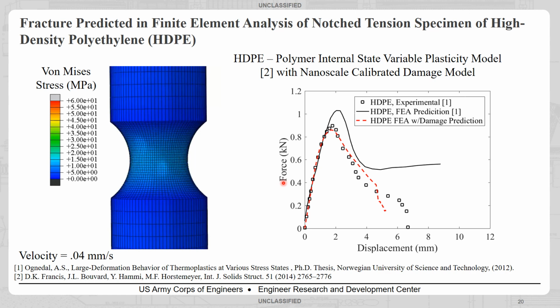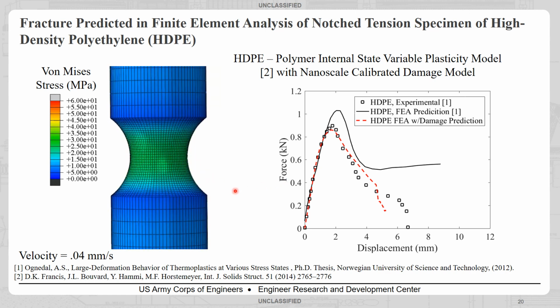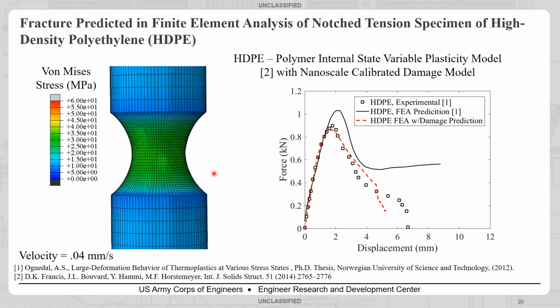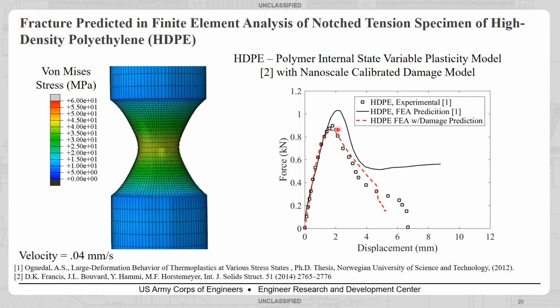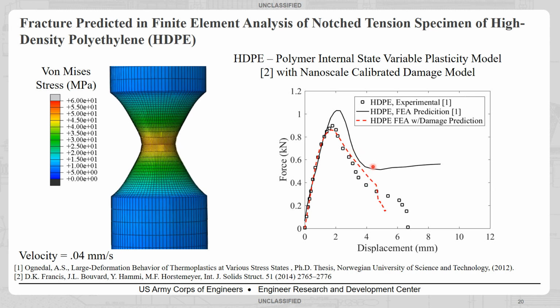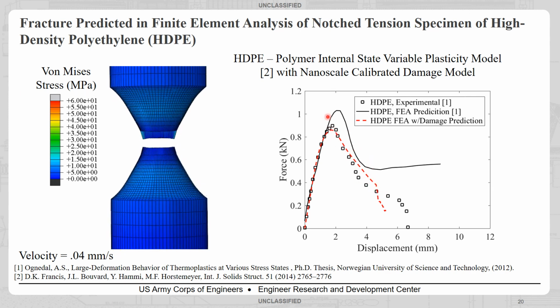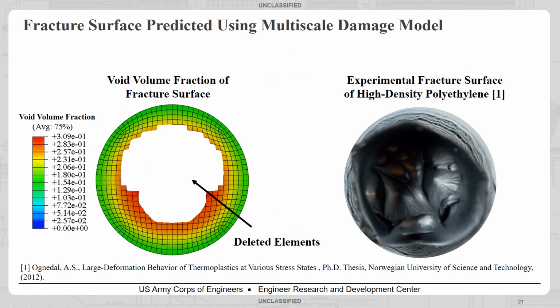So here we have this notch tensile specimen being deformed. You'll see necking start to occur, and then you'll see final fracture. And you see that our red curve does a much better job at predicting the experiments than the solid black curve that was published with this work. We get the failure strain to about 10% accuracy, which is much better than what they predict. What's interesting is that we are able to capture the fracture surface.